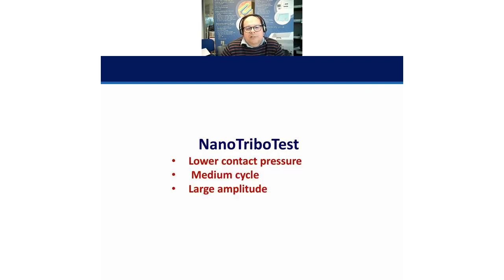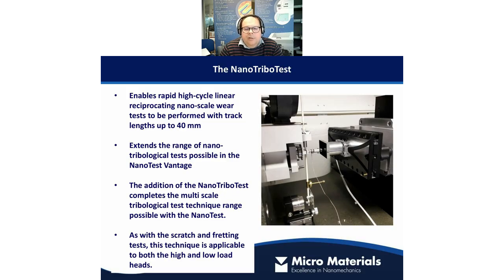So the NanoTriboTest is the final one of the techniques I wanted to introduce. Lower contact pressure, medium cycle, so tens, hundreds, maybe a few thousands of cycles. We're certainly not going to hundreds of thousands of cycles, and a larger oscillation amplitude. Like all of these techniques, we're using the same loading head on the instrument, the same loading heads as we use for indentation or for impact testing or any of the other techniques.